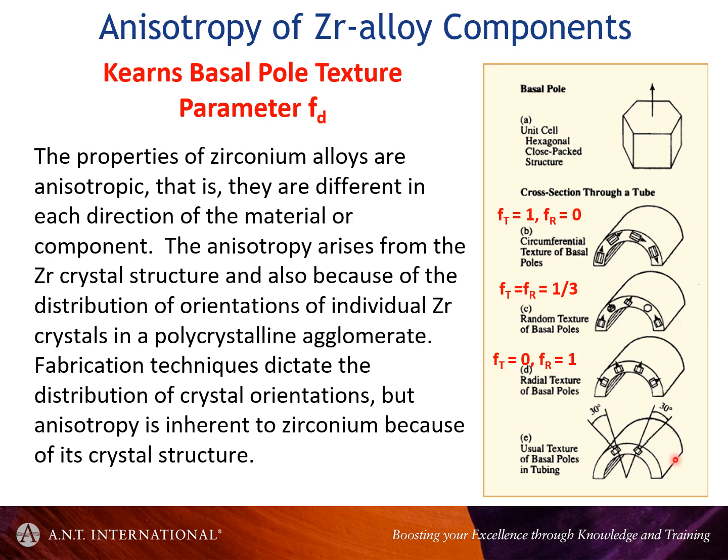For plate materials or tube reduction, pilgering type operations, you tend to get textures more like this. So fuel cladding gives you more like this texture. Extrusion of pressure tubes gives you more like this texture.